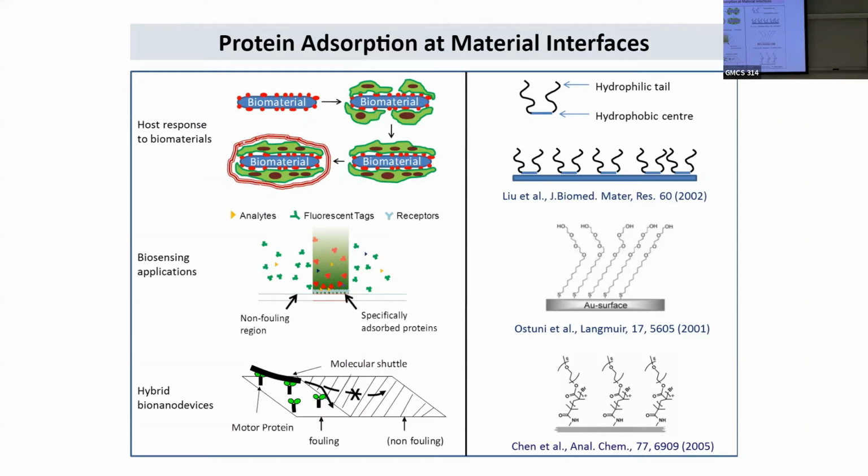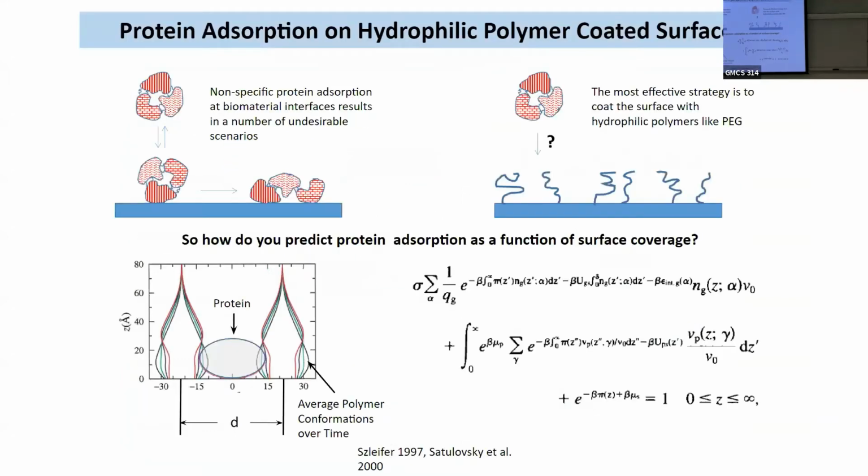And what happens in that scenario is when you have these hydrophilic polymers and you have this water, the protein obviously likes to stick to the surface due to multiple interactions. So the protein can stick to the surface because there is some weak electrostatic attraction between the protein and the surface, or there is potentially a hydrophobic interaction or attraction between the protein and the surface.